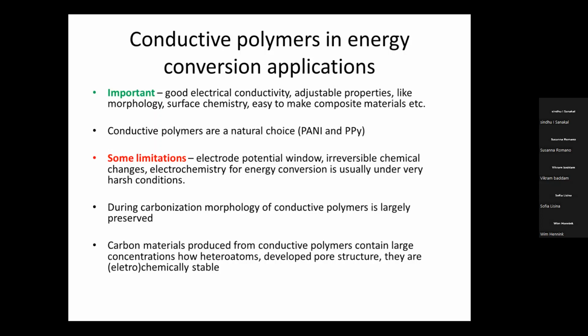And what we should also be aware of is that electrochemistry for energy conversion is usually taking place under very harsh conditions. So it's either highly acidic media or highly alkaline media. It's important because of the energy losses in the electrolyte. There are also quite frequently very high anodic or very high cathodic potentials. So we have to be very careful when we work with conductive polymers because they can change their properties irreversibly, and basically we can kill our energy conversion system.